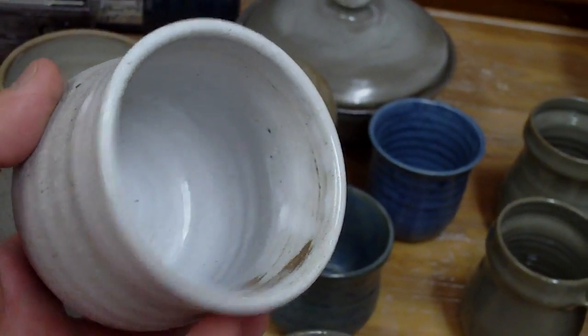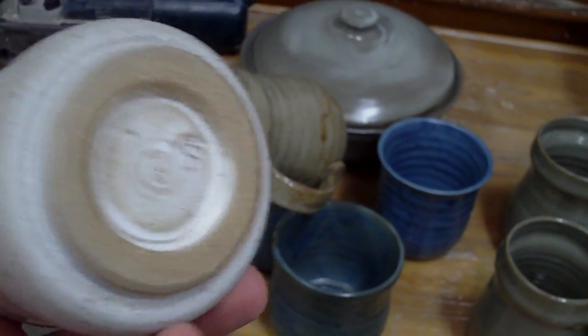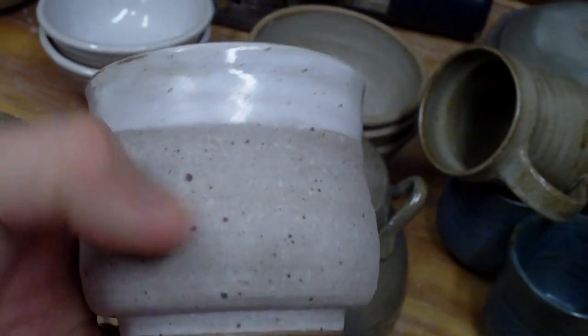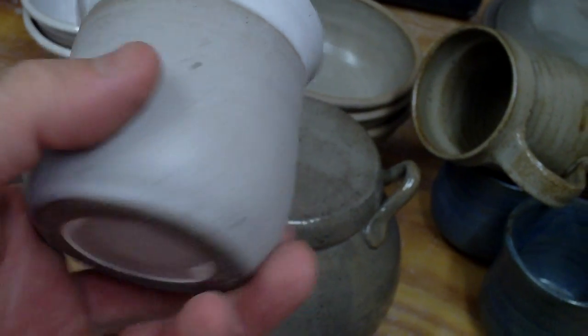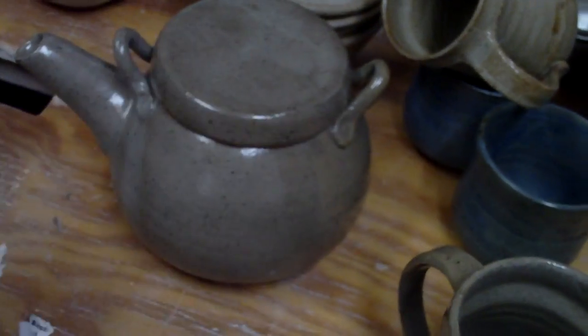Another t-bowl — these t-bowls have leach white on the inside and oatmeal glaze on the outside. Now this was in a different shelf than this bowl — that one is matte but smooth. These t-bowls, though, it's rough. Same glaze, different shelf, different shelf — it's just plain not fired up. Not fired, same thing here — not fired.